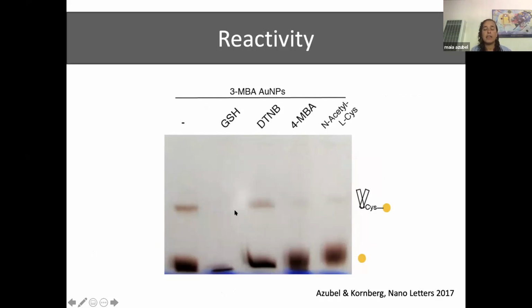What you're seeing here is a gel where I have a 3-MBA cluster and I change the ligand for glutathione, DTNB, the 4-mercaptobenzoic acid, or the N-acetyl L-cysteine, and then I incubate these gold nanoparticles with a small antibody that has a surface-exposed cysteine. So I have a free thiol on the cysteine. As hopefully you can see, when I have the 3-MBA, the reaction gives a more predominant band compared to all the other ones that are faint. At the bottom is just the gold nanoparticle.